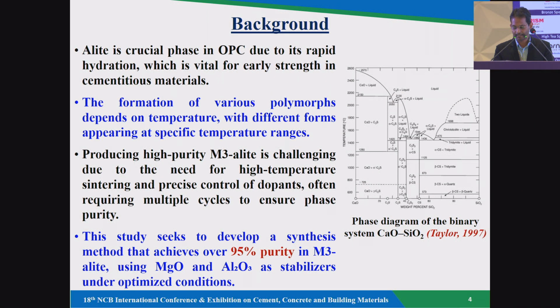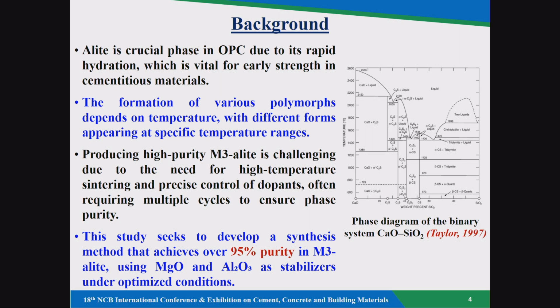I was discussing earlier that the formation of different polymorphs such as alite or belite depends on the phase diagram, in which as we move towards the right, the calcium to silica ratio will decrease, and the formation of C2S based polymorphs will occur. So our concern was towards the left side, the formation of C3S, the M3 phase was our target, and that target was achieved by addition of MgO and Al2O3. This study seeks the development of the synthesis of M3 alite using the solid state sintering process, which was done up to 7 hours, and we have developed about 1 kg of that M3 phase of alite within 7 hours of sintering time, with a dwell time of 4 hours and a ramp rate of about 8 degrees centigrade per minute.